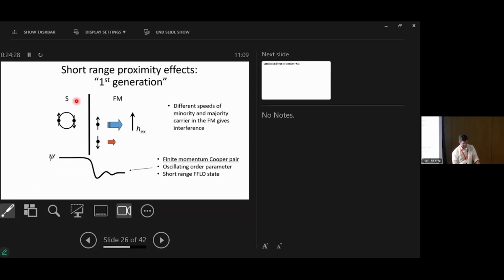Here's a Cooper pair singlet. You take these two electrons and put it inside a ferromagnet. Inside the ferromagnet, up spins are different from down spins because it's a ferromagnet. So the bands are split. So at the Fermi energy, the Fermi velocities for the up and down spins are different. So the different speeds give you some kind of interference effects. And that's a super fast cartoon argument as to why the superconducting order parameter has this kind of wiggly oscillation. It's a new type of superconductor that we've engineered by combining two materials together.